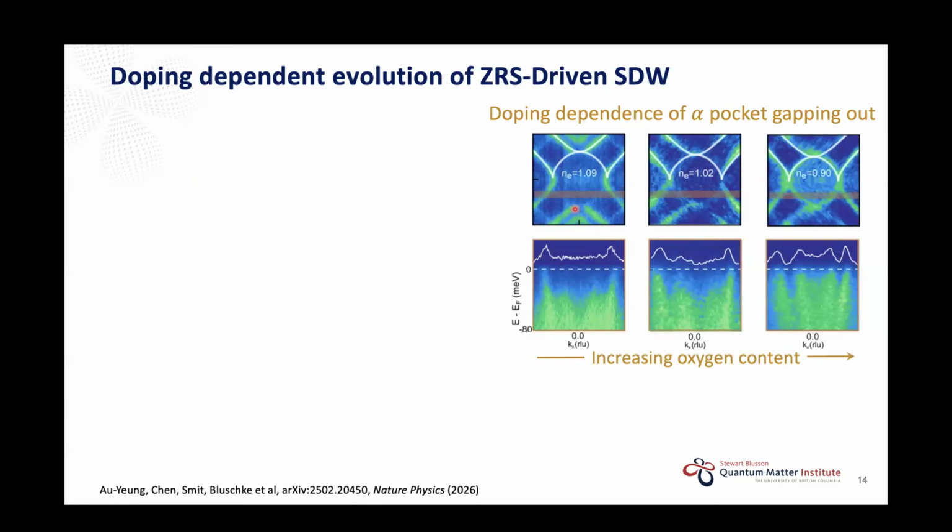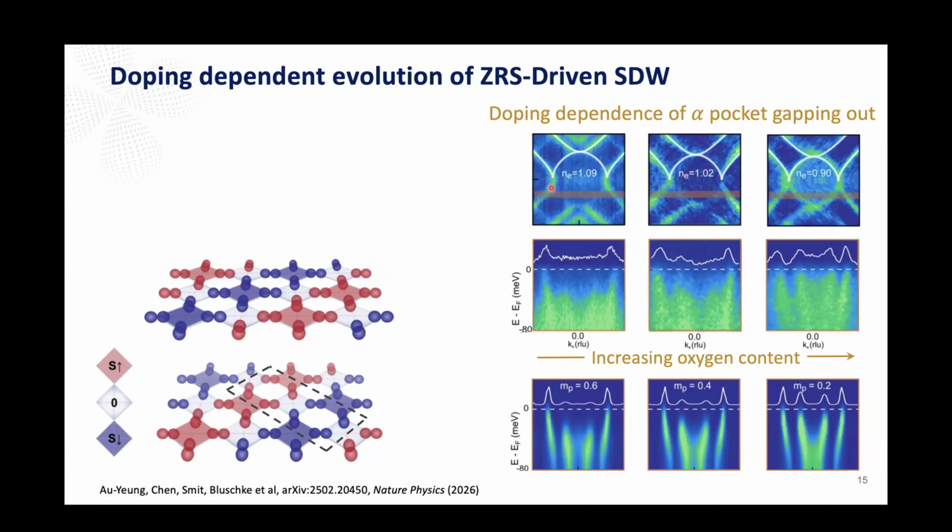Right. So from our model, what we are showing here is one domain. When we overlap this part to this part, this entire overlapping region should be gapping out, including the beta band. But each domain is very small, so you're basically having two orthogonal domains together. The result is that we'll only be able to resolve the gap around this area. One side of it will not be gapping out, and that's why we don't see the gap opening.